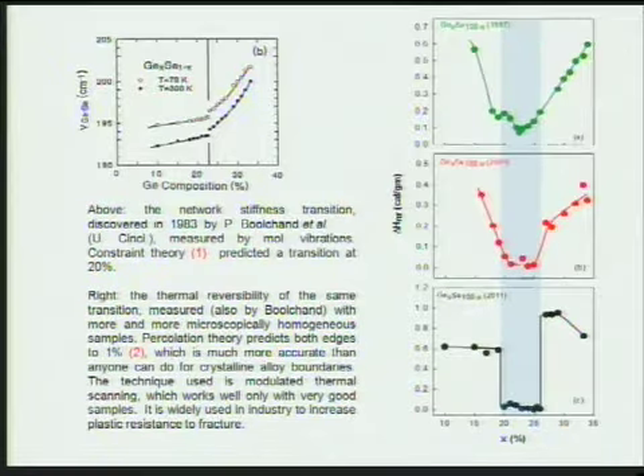And this actually shows this stiffness idea, where we measure a vibrational frequency of some atoms against composition, and you can see that when there are too few constraints, it's softer, and when there are too many constraints, it becomes more rigid, and there's a very abrupt transition from soft to rigid, flexible to rigid.